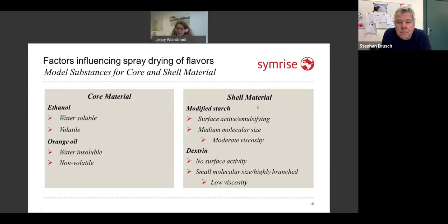As shell material, I chose a modified starch, an OSA starch, which is very surface active, a very good emulsifying material. It has a medium molecular size and therefore a moderate viscosity, which means I can take comparatively high contents in my mixtures. And the dextrin: the dextrin has no surface activity at all. It's a small molecule, highly branched, and therefore even at high solid content, I will have very low viscosities.